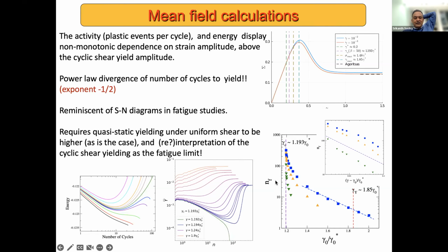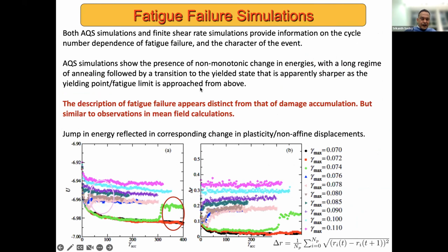One can therefore look at the number of cycles to failure. And one finds, as some people have found in the literature recently, an exponential dependence of this failure time at sufficiently large amplitudes above the yielding point, but close to the yielding point, a power law dependence with an exponent of -1/2. Now, this is the kind of behavior that's very much seen in computer simulations.